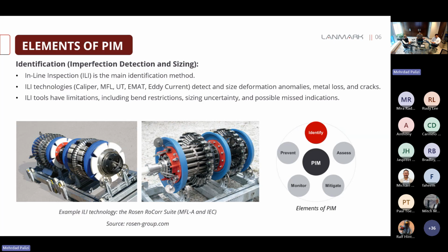MFLA is used for detecting and sizing metal loss, such as corrosion and pitting. IEC provides high-resolution detection for internal metal loss. Both these technologies have a minimum bend radius of about 1.5 times outside diameter.